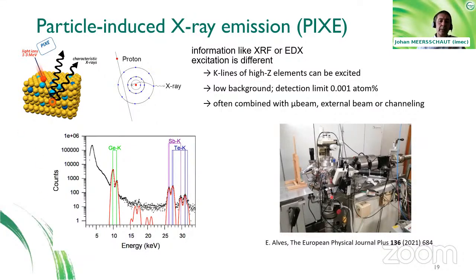The example which is given here, the setup in Portugal, shows that a piece of art can be put in place in atmospheric pressure in front of the microprobe. This is also an approach pursued at, for example, the Louvre in Paris to study pieces of art. In that case, the light ion can penetrate like 10 centimeters of air. Typically, we enlarge the amount of helium in that environment to make it as minimal as possible. But the emitted X-rays can be detected with an X-ray detector, just as you would do with X-ray fluorescence spectrometry. So, in fact, this photograph illustrates that experiments can also be done in air.